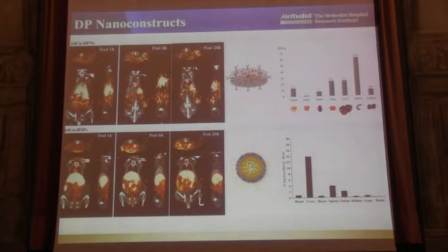And as I told you, these particles do not get very easily into cells, including macrophages. We have live cell microscopy studies with J774, bone marrow-derived monocytes, so primary cells as well as cell lines, showing this particle dancing around the macrophage for a couple of hours without being uptaken, without stimulating the monocytes. We have side comparison with polystyrene particles. All the polystyrene particles are inside the macrophages. These are still dancing around.